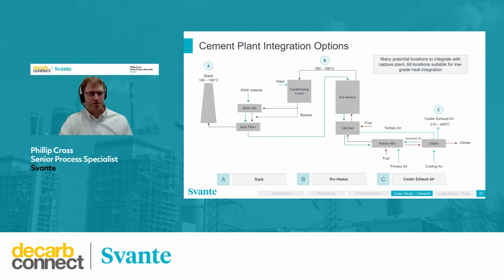So this is after the preheater. It's for CO2 capture and heat integration. The pro is that this is a really hot stream. So this is coming off of the calciner where most of the CO2 is produced. So you have much higher CO2 concentrations. However, there's really high dust loading in this. And if you integrate at this location, you're also going to have a greater impact to the cement process. So the stream coming off of the preheater is often used to dry the material.